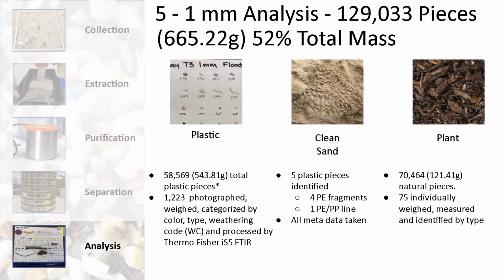For the 5 to 1 millimeter category, you'll notice that 52% of that total mass was just in this chamber. So there was a significant amount of microplastics or micro debris in this. Again, all of these particles were photographed, weighed, categorized by their color, type, weathering code, with a subsample processed by the Thermo Fisher IS5. In the clean sand, we found 5 pieces. Same metadata was taken from that. And with the plant, beyond just visual confirmation that it's natural material, we threw it in the IS5 to make sure that it is cellulose and not a synthetic piece.